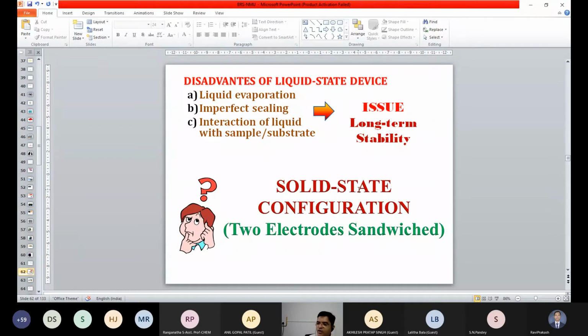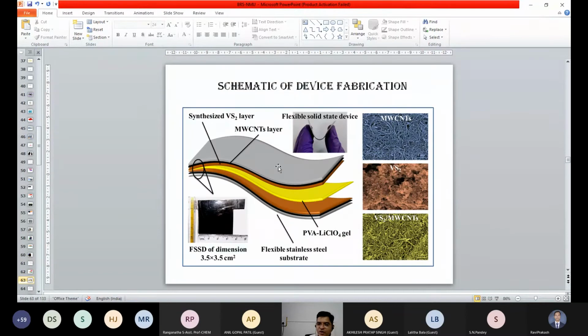So instead of using one electrode, you can use two electrodes. Instead of platinum, you can use both vanadium sulfide coated with the carbon nanotube as one electrode, and the other electrode is the same. If both electrodes are same, we can say it is a symmetric device. So what we have done, we have taken the stainless steel coated with the carbon nanotube, vanadium sulfide coated. The same electrode we have also used, and in between these two electrodes, we have used a conducting electrolyte, LiClO4. Actually, we have tested different electrolytes, no doubt, right? So LiClO4 is a conducting electrolyte.